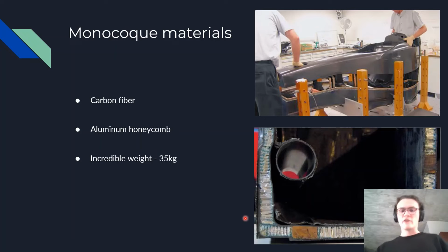All monocoques are made of carbon fiber and epoxy. This is just because that's really the most dominant material that teams have found, and it's just the strongest, really. In the middle, though, oftentimes the aluminum honeycomb is added. You can kind of see a nice cross section down here.